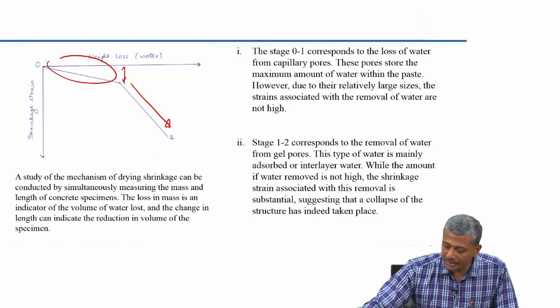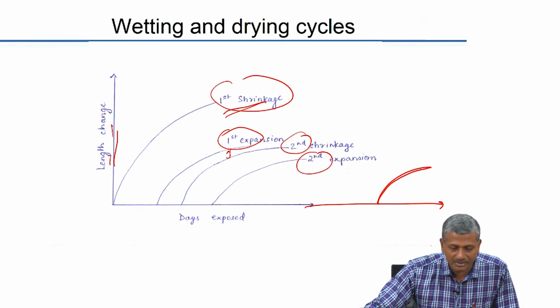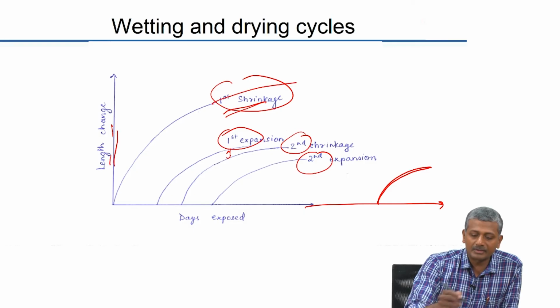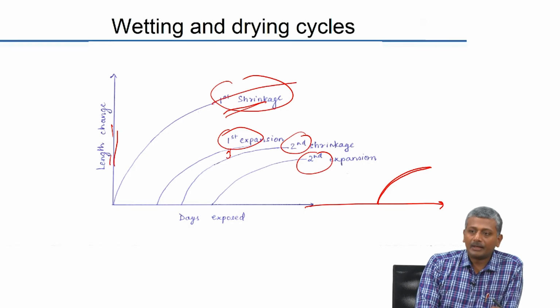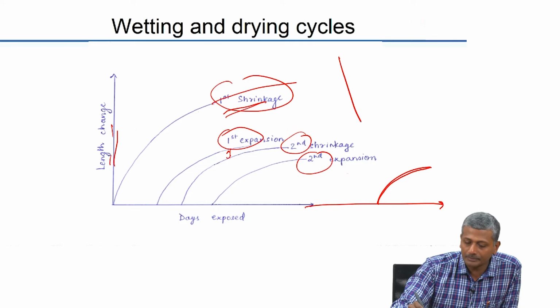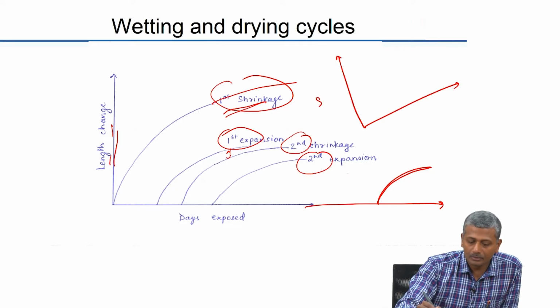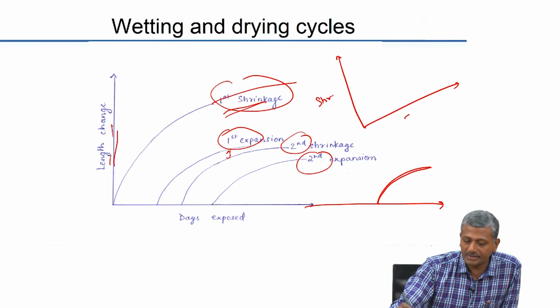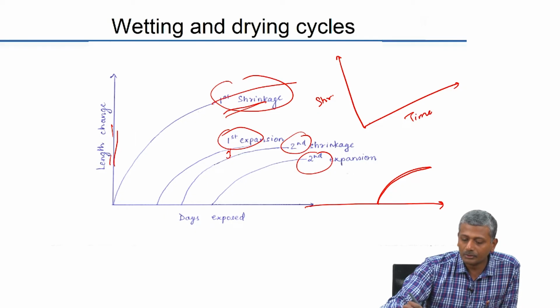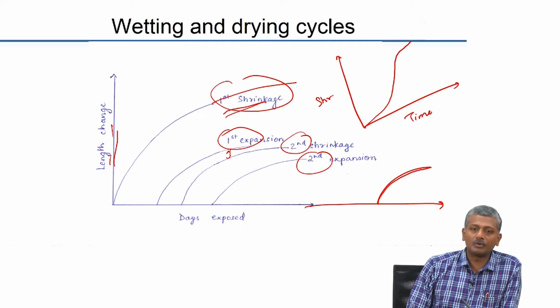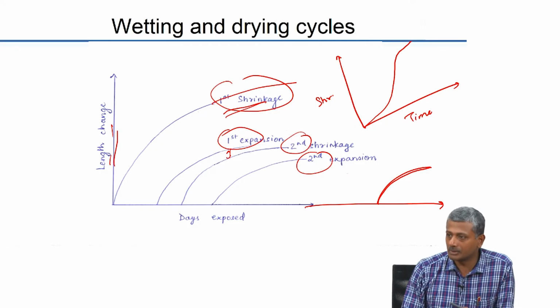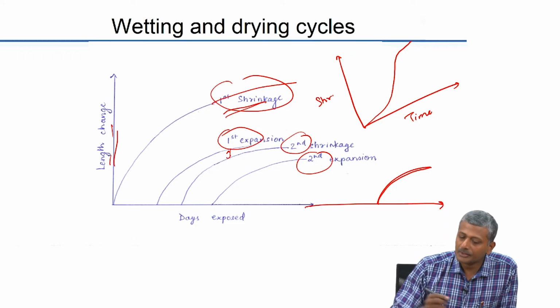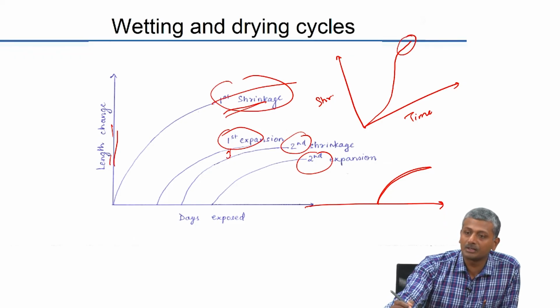Okay. Now, of course, I talked about the fact that the shrinkage itself will start stabilizing, the rate of shrinkage will keep reducing, and generally if you plot your shrinkage level versus the time on a log scale, you will get some sort of a relationship like this. An S curve will generally be obtained when you do a log scale plot of the same points. So, what we need to do is control or continue the experiments until at least this ascending branch starts stabilizing.